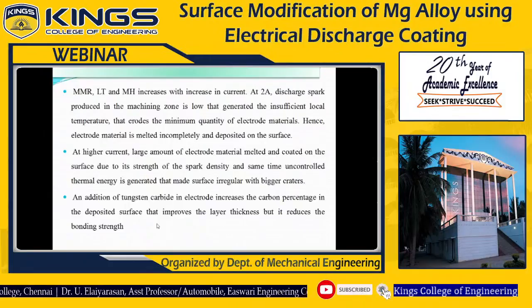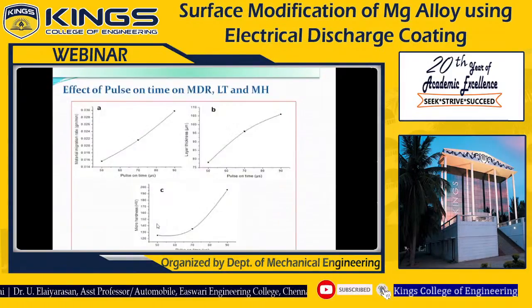An addition of tungsten carbide in the electrode increases the carbon percentage in the deposited surface. That improves the layer thickness but reduces the bonding strength. Here I have given pulse on time on MMR, LT, and MH.